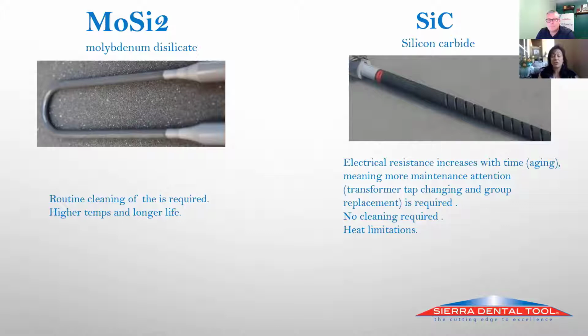And those are great heating elements. They allow you to go to a very high temperature, so you're not limited with zirconia. If you have a zirconia that sinters really high and you have this kind of heating element, no problem at all. The only downside, which I don't really consider a downside, is that you have to do some maintenance and you need to calibrate. And these also need to be purged, which we'll talk about in just a minute. They do have a longer lifespan than the silicon carbide, which you see on the right side.